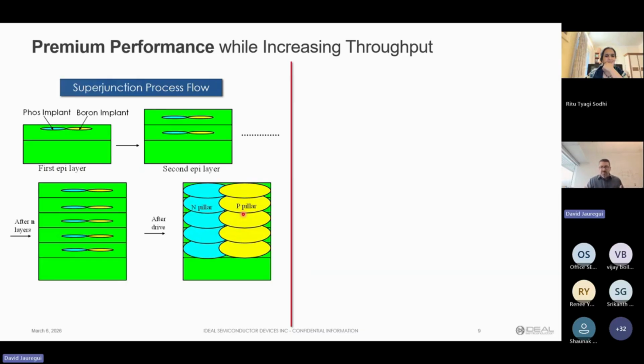This gets into how fabs operate. You start off with epitaxial, and you implant a phosphorus species and a boron species, phosphorus being N type and boron being P type. And then you mask it, you implant phosphorus, you mask it again, you implant boron. And then you grow another layer, then you mask again, you implant, mask, and you do that multiple times until you get to the final structure, and then you drive it in. Well, if you ever get a chance to work in a wafer fab, the number of masks matters, meaning that it takes longer to process, meaning that the cost to manufacture is higher.